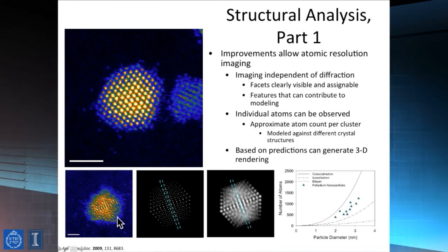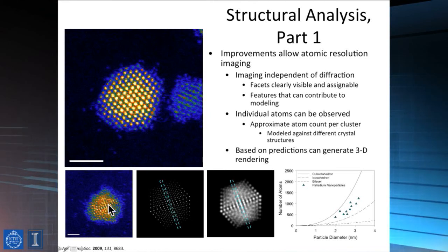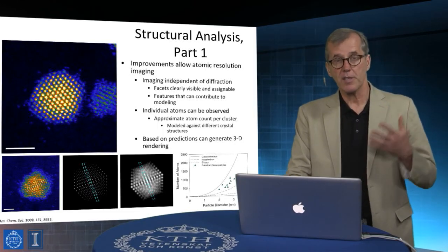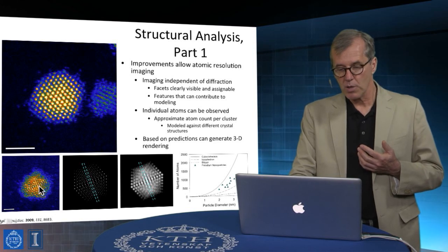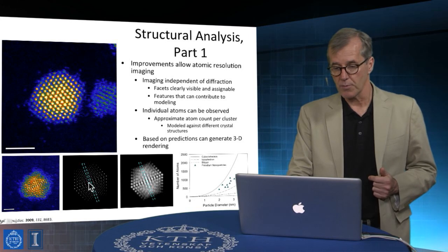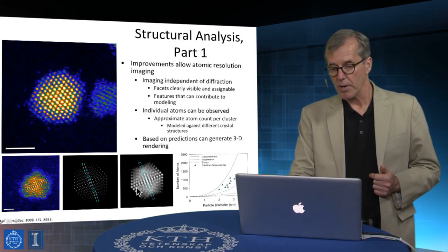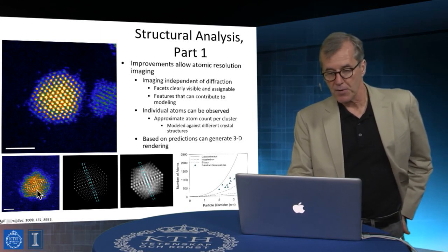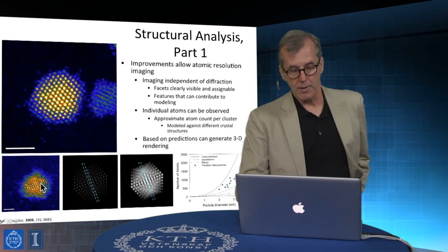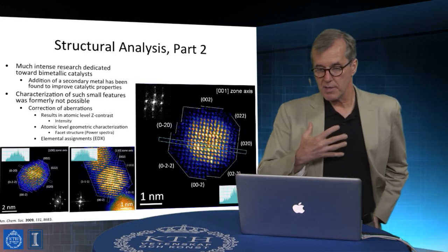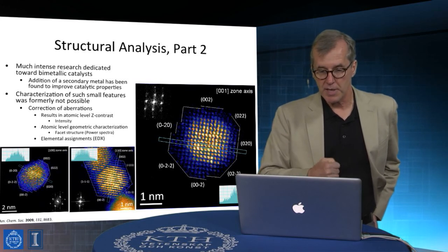But actually, if you do theoretical models of this cluster, it's got not the structure of the bulk metal, which is face-centered cubic. This is actually a small cluster which is grown with an icosahedral crystalline form. And that's a theoretical model that illustrates the specific orientation of that icosahedron. We can go through and deeply analyze complex speciations.